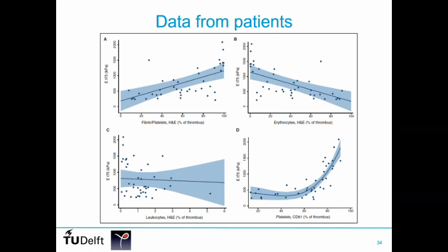And this is something that you would intuitively expect, right? If there's more fibrin or there are more platelets, then you expect a denser network, and you expect that network to be stiffer. Since they are almost complementary with the red blood cell concentration, you can see the inverse. If you've got a sample with a lot of red blood cells, then you get softer behavior of these samples.